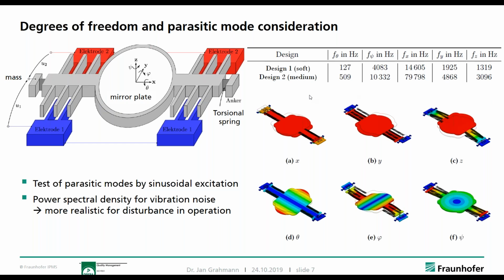So that means each of these parasitic modes I can, by intention, excite by using a sinusoidal excitation. When I use a vibration setup and have a certain sinusoidal frequency driving the scanners, then they would react quite strongly when that sinusoidal frequency hits the frequencies shown here. That is one point. So you can measure that way how strongly the mirror reacts to these parasitic modes in resonance.